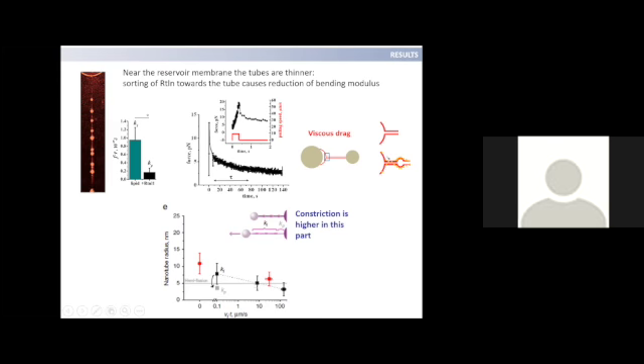This radius is below the minimum limit for the fission of the tube, but at low forces, which are more comparable with the physiological ones that the cytoskeleton can exert, this radius is higher than the limit. But if we use this new bending modulus that we obtain from the thinner part, we can see that the nanotube radius is below this hemifission limit. So the conclusion is that the reticulon is constricting the nanotube dynamically.